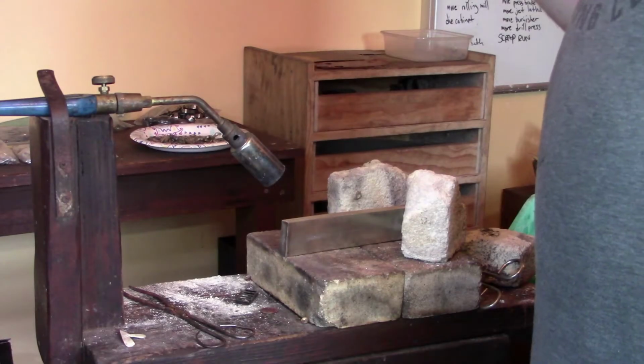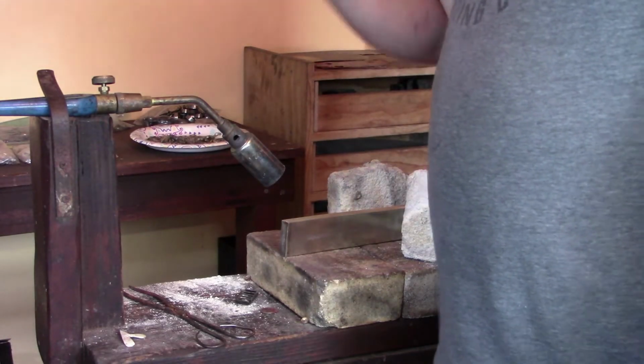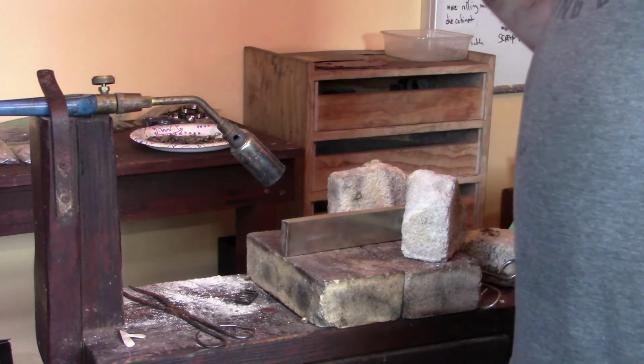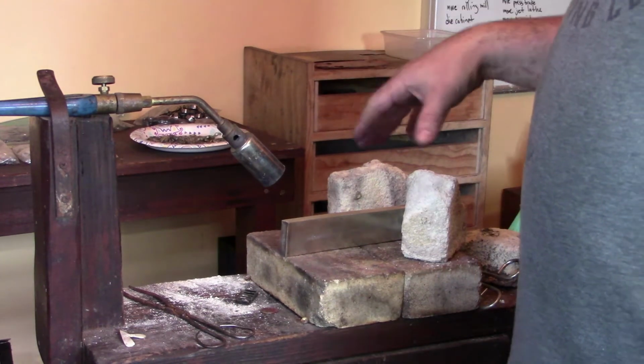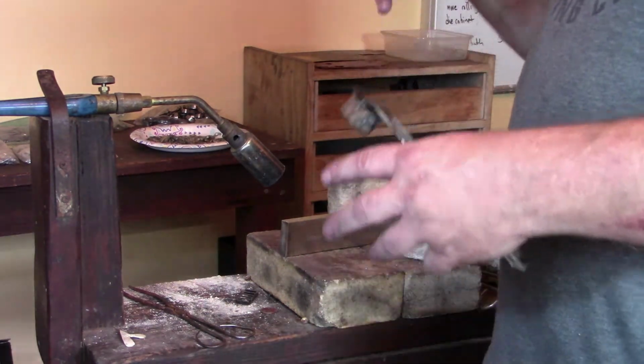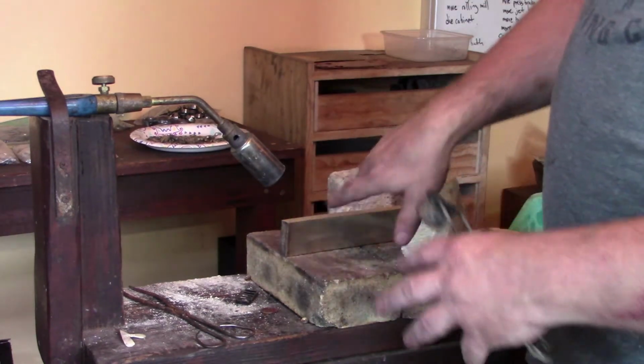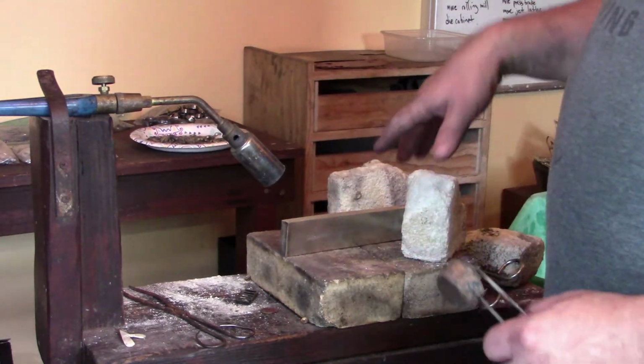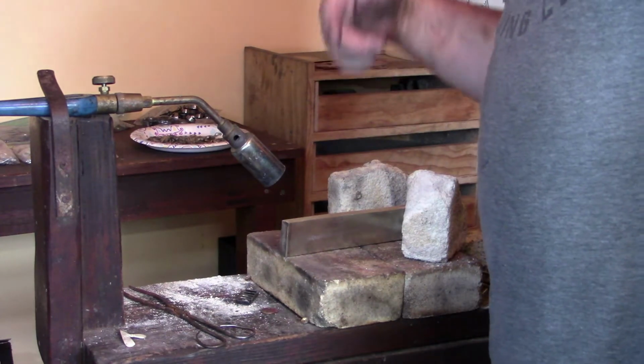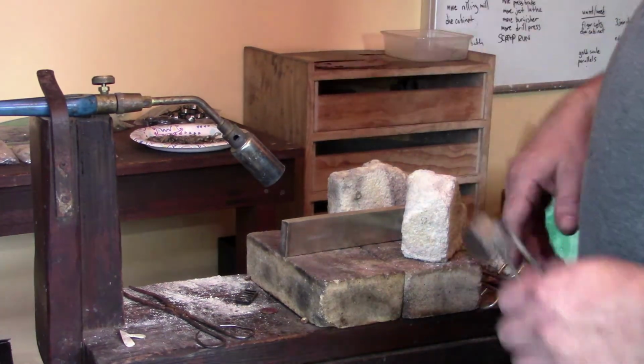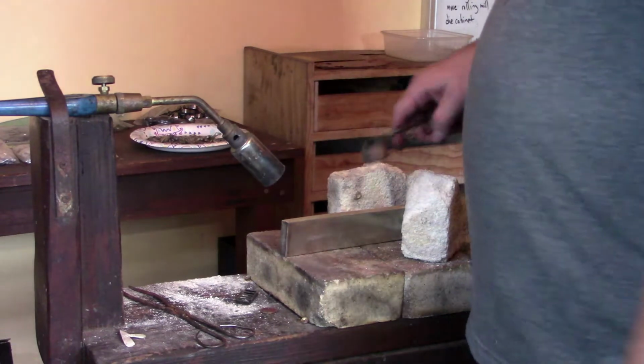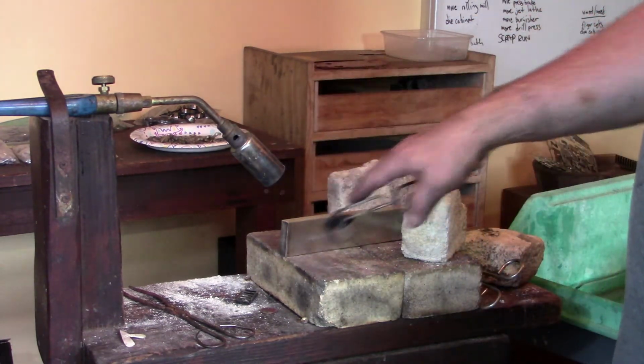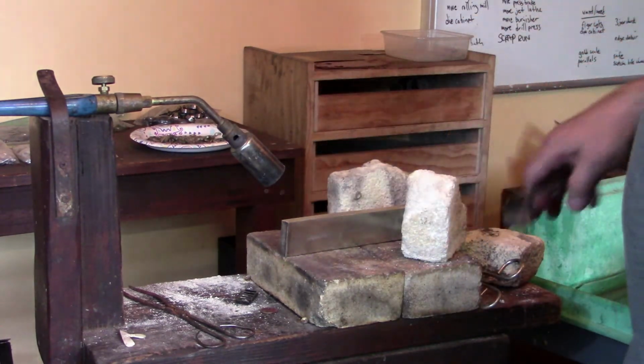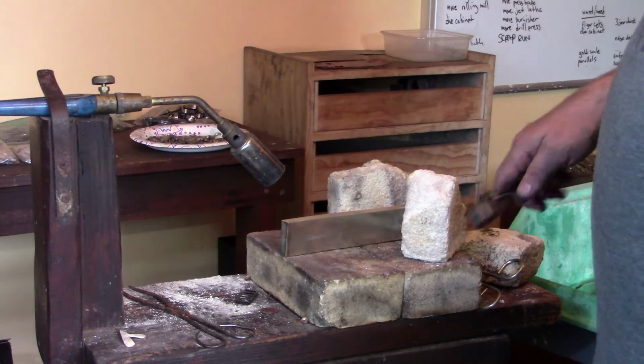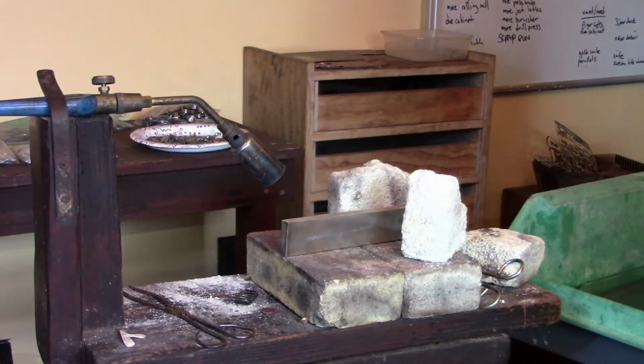With sterling, it's important to constantly keep it annealed. I can't stress it enough, because what happens is the part will start to crack. You'll get cracks and crazing and all kinds of trouble all over the material. It won't stay flat. If you don't keep it annealed and keep it soft while you're working it, it's just a total pain. So what we're doing is using a propane torch to heat this up red hot, and then we're going to quench it in an annealing bath that has some acid.